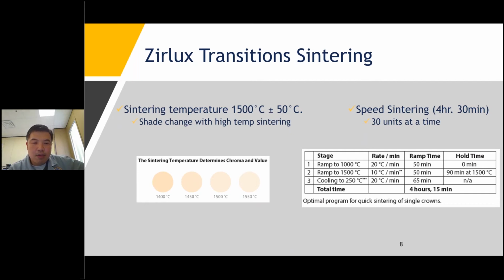Okay, the example is pretty much right on the side here that tells you that this is what it will look like if you are firing the same shade puck and the firing temperature is different, you will get different results. So this is a very interesting material. Why I say that is because you can actually control your zirconia now. Instead of having an A2, you can actually have an A2.5 by changing your temperature. Or you can get an A1.5 by lowering or raising your temperature. That helps you control your shade better, so that you know what shade you're going to get.